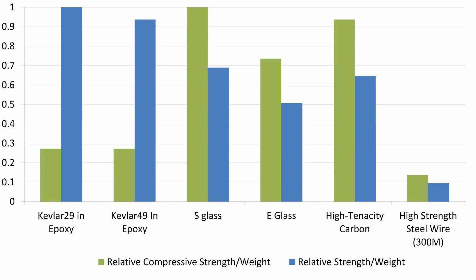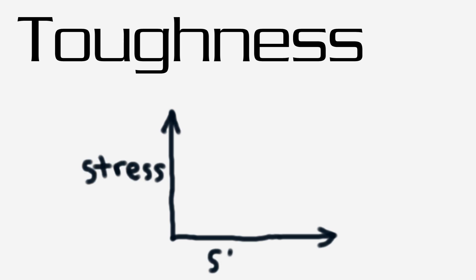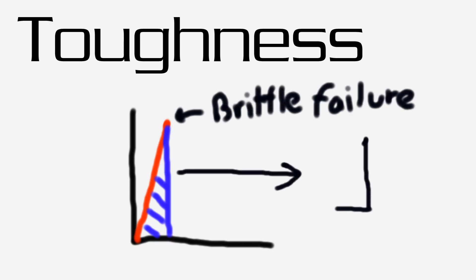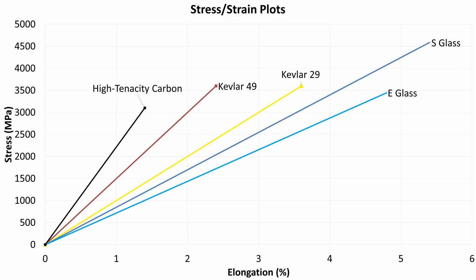The stiffness of carbon doesn't come without a high cost. If we look at the elongation of all these materials, carbon has almost no elongation — only about under 1.5% for generic carbon fiber. This leads to a problem with material toughness. Toughness basically defines the area under a stress-strain curve, which shows how far a material moves for a given amount of stress. Assuming brittle failure modes, the area under the curve is basically proportional to the elongation multiplied by the ultimate tensile stress. With S-glass having really high tensile stress and really high elongation, it is by far the toughest of these materials — followed by E-glass. You're going to want to use glass fibers wherever you experience impact loading and need toughness in your material.